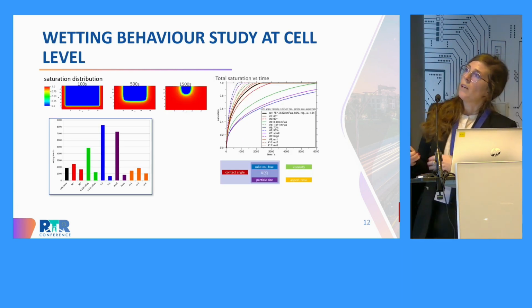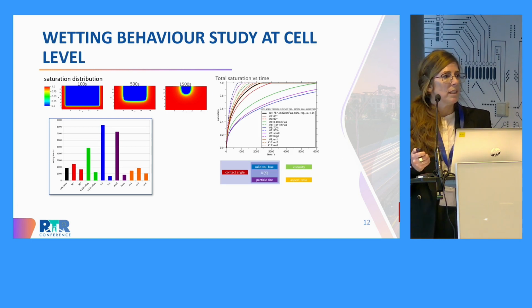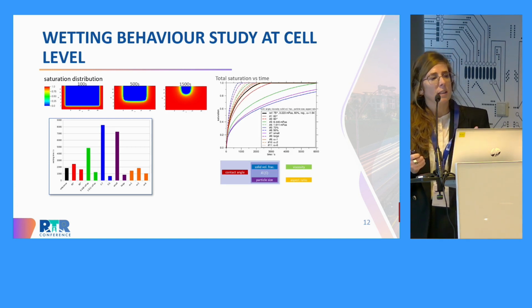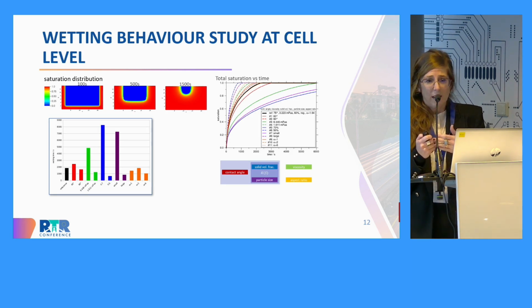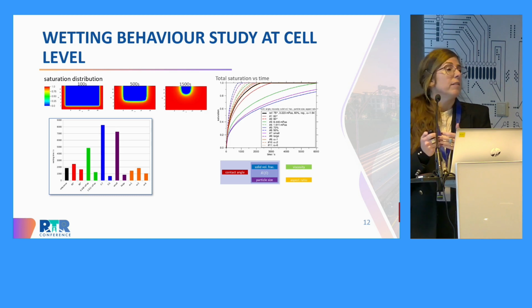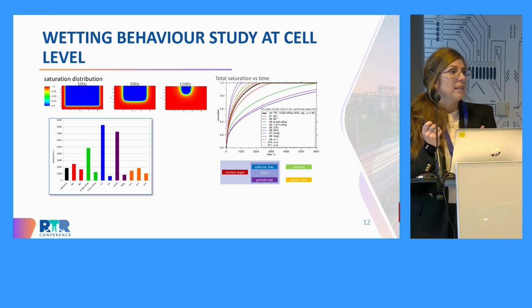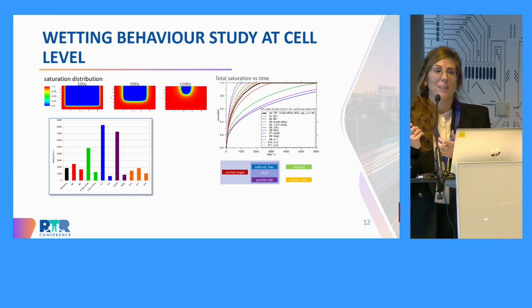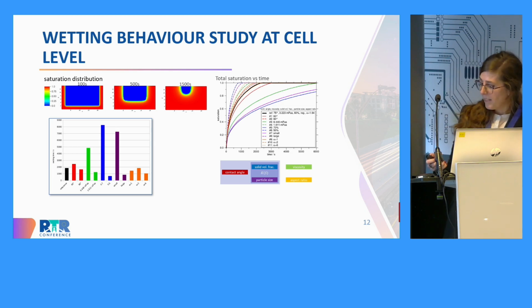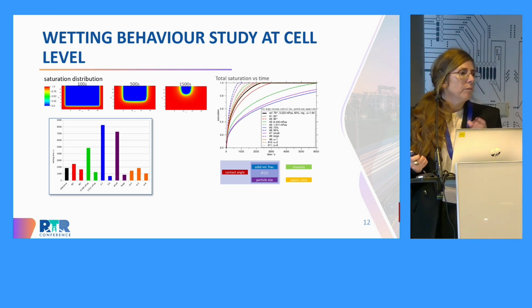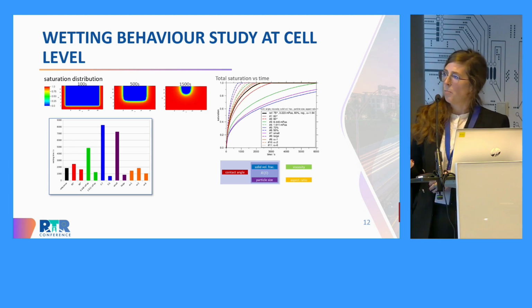Another one was on the wetting behavior. With this multi-scale approach, we were able to predict certain pressure-saturation plots. And this is again crucial, because if you want to avoid any gas entrapment, and you need to optimize and obviously accelerate the electrolyte filling, you need to know this kind of plot in advance, because otherwise maybe you don't reach the full minimization of the gas entrapment.